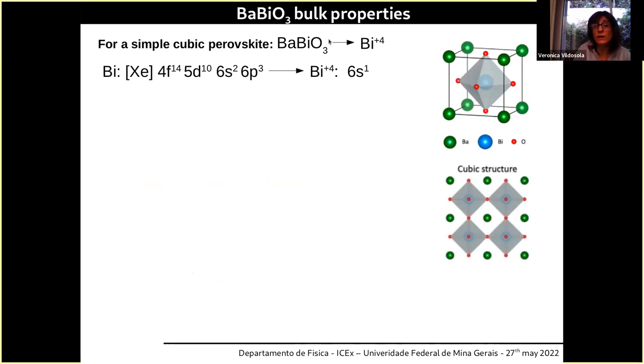The BaBiO3, the simple formula unit, corresponds to a crystal structure that is a perovskite, where you have barium at the corners, then bismuth in the center, and an oxygen octahedron around the bismuth. If you do a simple formal balance count, barium is 2+, oxygen is -2, but you have 3, so -6. So bismuth would in this crystal structure be forced to be 4+, right? Bismuth is a very heavy element. In the last shells, you have 2 electrons in the s band and 3 electrons in the p band. And to be 4+, these 5 electrons give 4 to the system and you end up with the s band half filled, right?